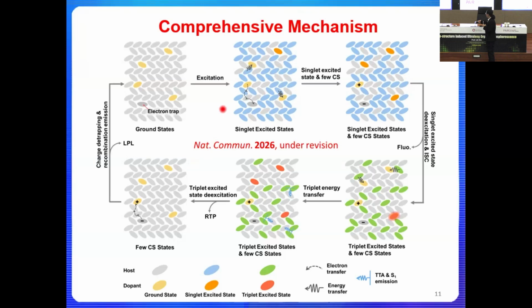Now, after that, at a different time scale, this charge separate state can migrate and recombine, and this will give you the persistent luminescence. So you will have different signals at different times with different brightness that capture the time frame and the light emission of the system.